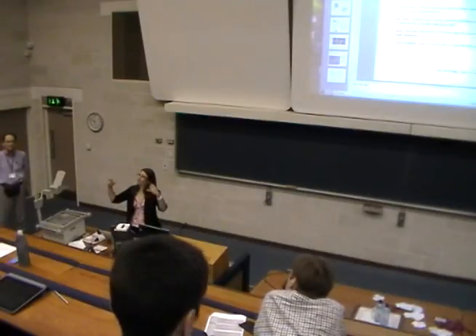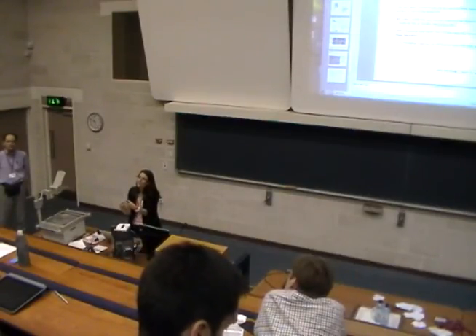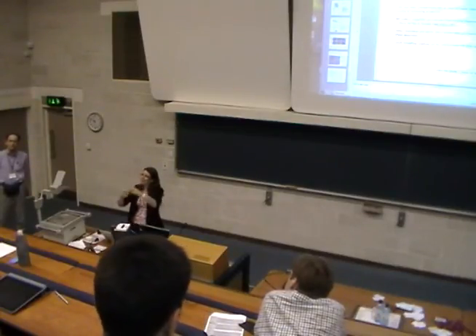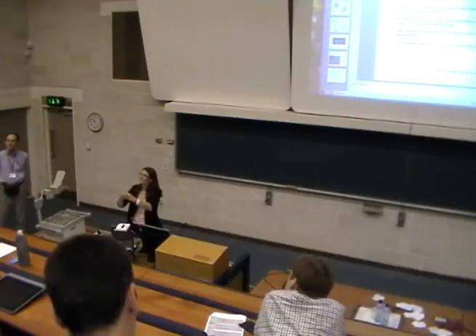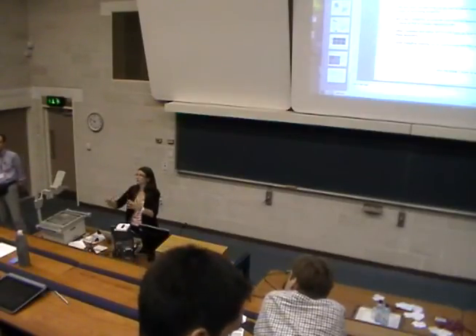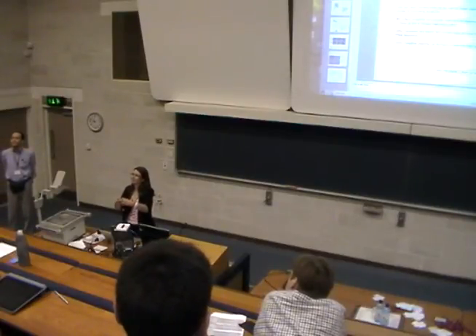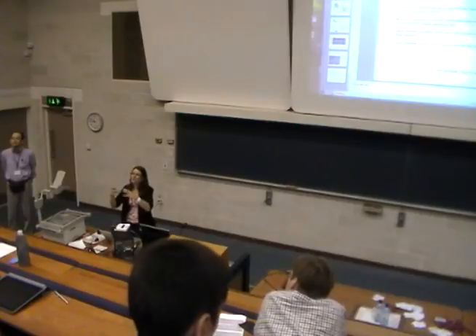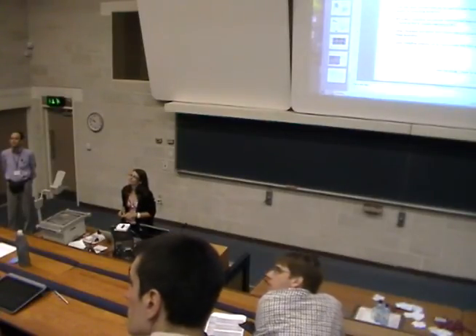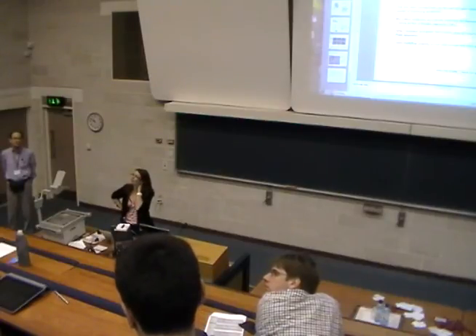Also, you could think of it kind of like a fractal aggregation type effect. When particles come together in a cluster, they add and add and add to the cluster. So the way the cluster grows is not going to be a perfect crystal. It'll add randomly. You can have vacancies in the cluster. It grows in a very disordered way. A fractal structure has to have a sticky surface, and once they get there, they cannot move to an equilibrium state.